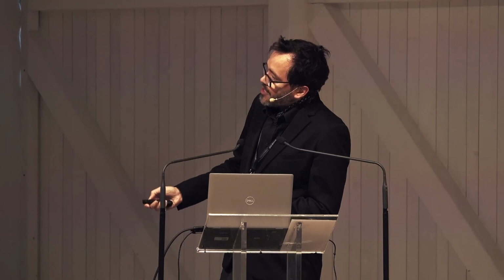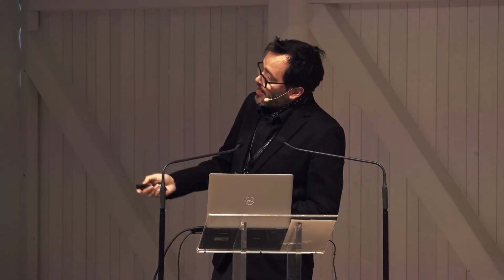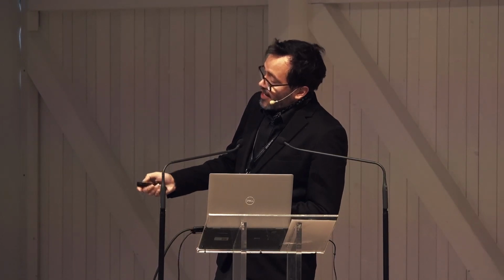The interaction between the anode material particles, which can have different shapes and different sizes, and the interactions between these aggregates of carbon binder and solvent. Okay? Then we solve Newton-like equations by using force fields describing the interaction between the particles. Based on these simulations, we converge to an equilibrium state that will represent the virtual or digital twin of a slurry, right, in periodic boundary conditions.